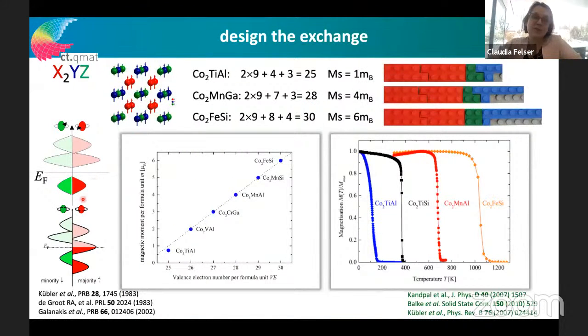I don't have to explain at length that Heusler compounds are so-called half-metallic ferromagnets. We can have Heusler compounds which are semiconductors, even with so many different elements and even with magnetic elements in the material, like Fe2VAl, which is a non-magnetic Heusler compound, even semiconducting, for example. This is simply by counting the electrons, like we have III-V semiconductors, and mercury telluride is a semiconductor. If you have a closed shell system of all the valence electrons of the material, we end up with a semiconductor.